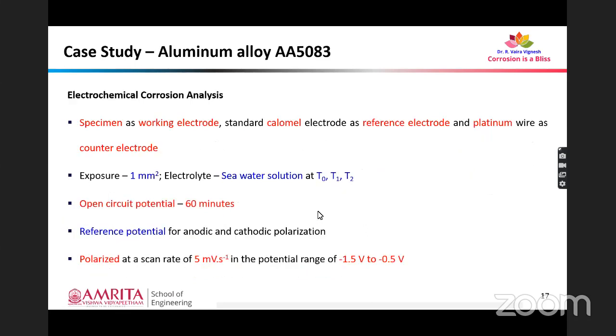So let us take a simple case study where I'll discuss how to calculate the values of corrosion potential and corrosion rate based on this potentiodynamic polarization. In this, we have a specimen as working electrode, standard calomel electrode as reference electrode, and platinum wire as counter electrode. The exposure area is 1 mm square, and the electrolyte solution was simulated seawater, that is 3.5% sodium chloride dissolved in deionized water at room temperature. The temperature can be varied. That is also one of the parameters that influence the corrosion rate of the materials.